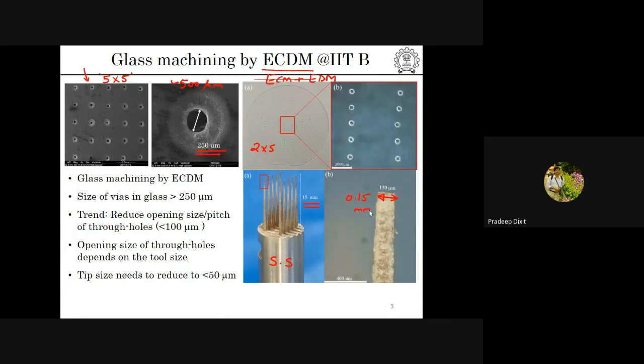So far the results are quite promising. But if you look at the current trend, especially for MEMS packaging and electronic packaging applications, people are going towards reducing the opening size. At present, the opening size is roughly about 250 micrometer, but the MEMS industry wants to reduce the overall size of these through holes. And what is the target? The target is roughly about 100 micrometer. It means that we need to fabricate through holes having a diameter of 0.1 millimeter.